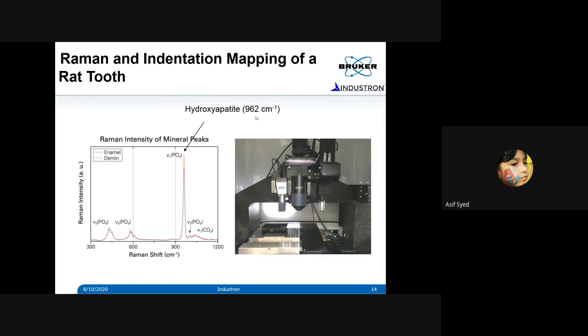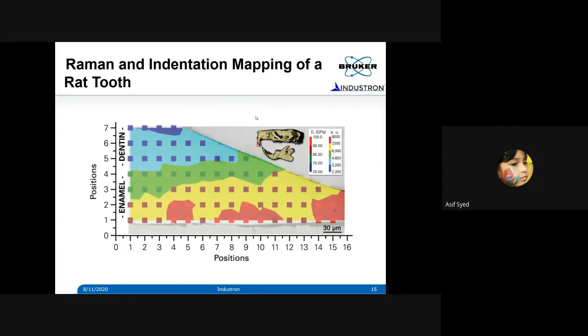If you see a higher intensity, which means the mineral content is higher, can you correlate that with the mechanical property that you measure? That is what we are going to see in the next slide, where you can see that in tooth material, there are two things: the dentine and the enamel. Enamel is the hardest part and the dentine is the soft one. So when you chew something, you need to have this combination of soft and hard structure, that is built into our tooth material, right? So dentine is generally soft. And if you look at the mineral content, that is what I'm showing over here in this marking.